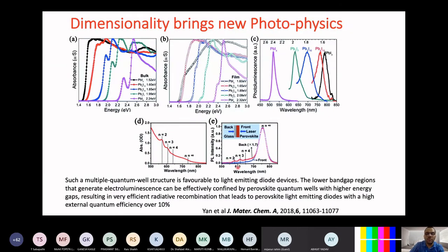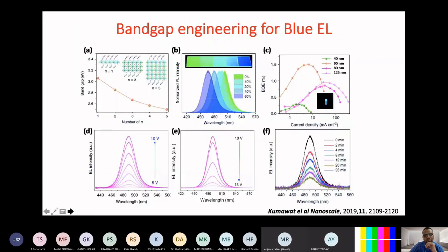And the same thing can be seen in the photoluminescence as well. You see the energy being transferred, because the higher energy photon can transfer its energy to the low energy band gap material available in the same film. So when you mix these things, they all come together in a single film. You have various different band gaps of the perovskite, and all the emission gets dominated by the low band gap semiconductor, because all of that energy gets funneled into the low energy emission by the Förster energy transfer mechanism.